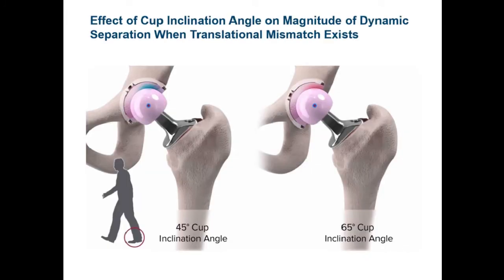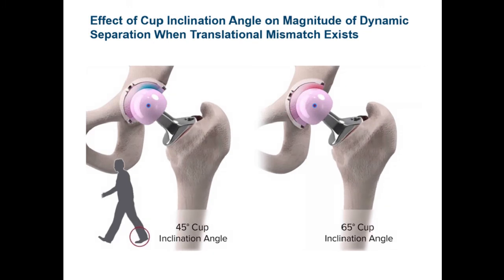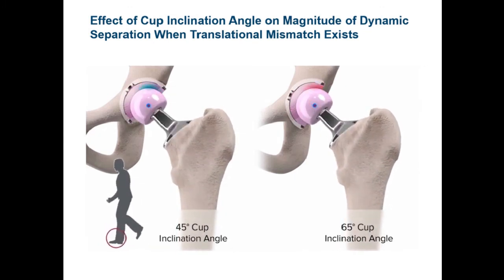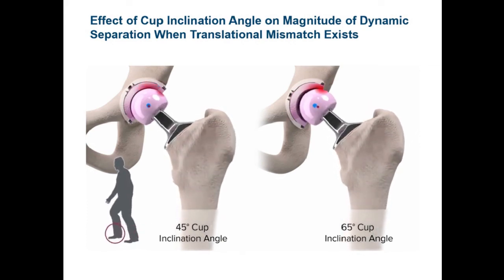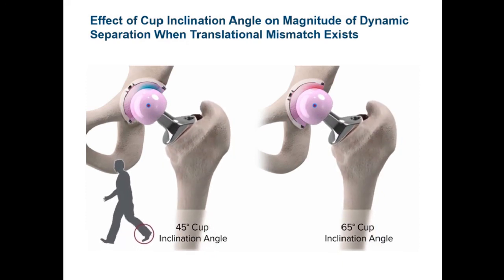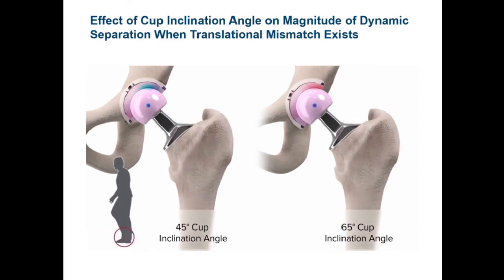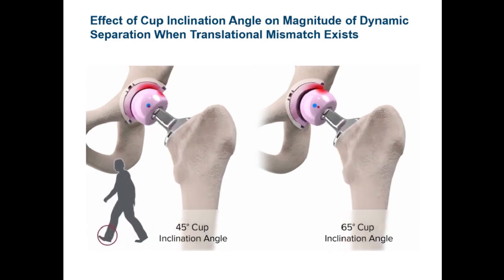It's been shown that applying a translational mismatch between the femoral head and the acetabular cup would lead to dynamic separation and edge loading scenarios where the femoral head contacts the edge of the acetabular cup, causing inferior tribological conditions where the wear of, for example, a ceramic on ceramic would increase significantly compared to a well-positioned implant. And you can see that the combination of a translational mismatch with a steep cup inclination angle would increase the severity of edge loading even further, further increasing the wear rate of such bearing material.